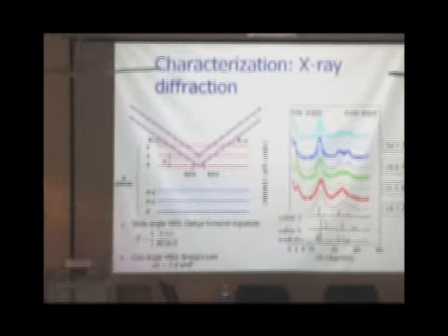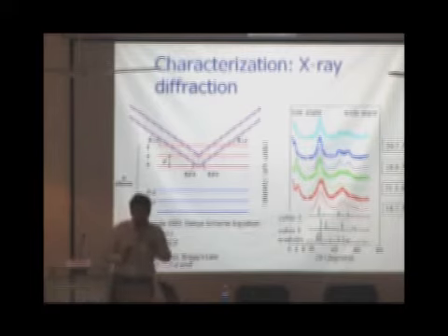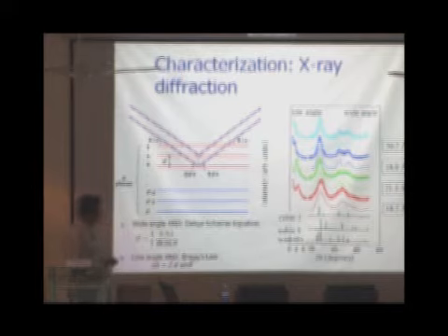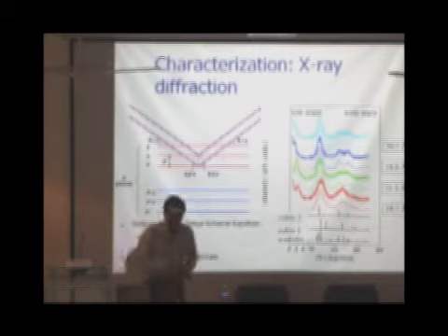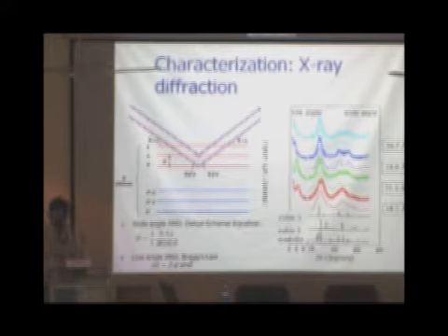We do an X-ray diffraction experiment. There's something called the Scherrer equation, from which you can get the size of the nanoparticles, or the nanocrystals to be exact. I should be more careful using this word, nanocrystals, because the X-ray diffraction size that you get is only for the crystalline part. And if Professor Mehta is angry with me one of these days, I just don't go to the TEM, I go to the X-ray diffraction and immediately get the size of the particles. But normally he's not, he's in a good mood.